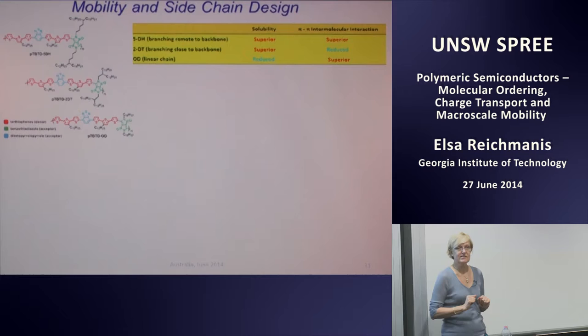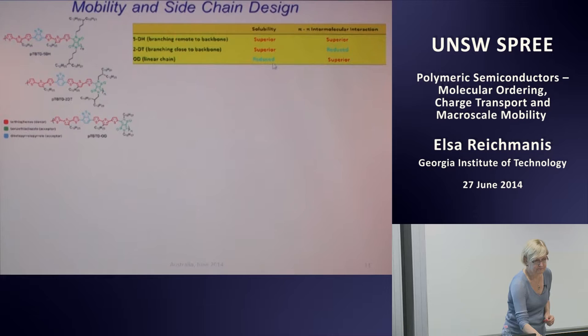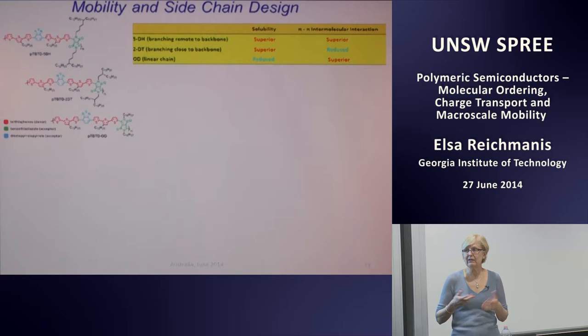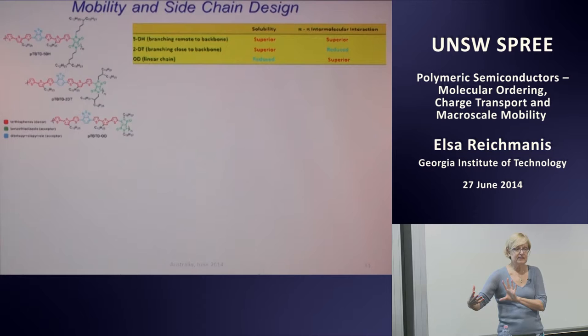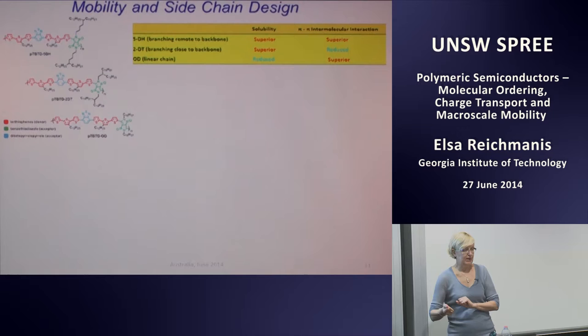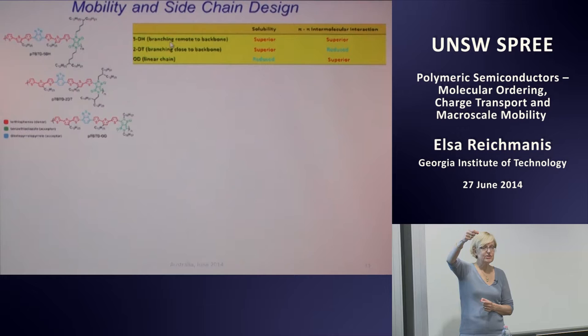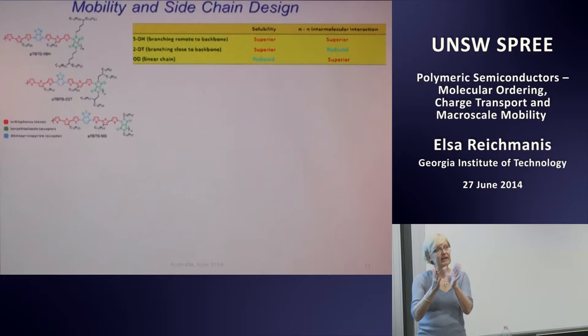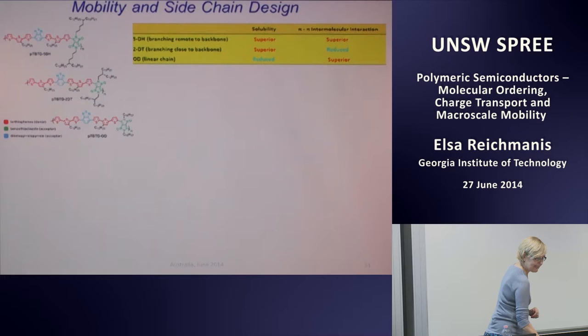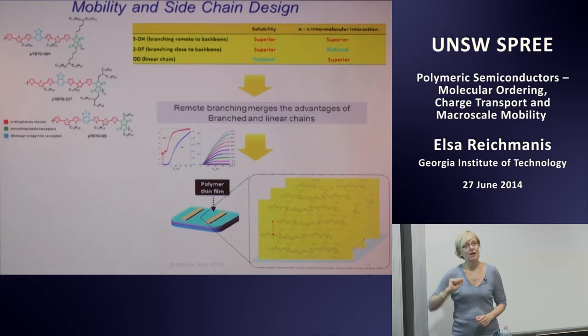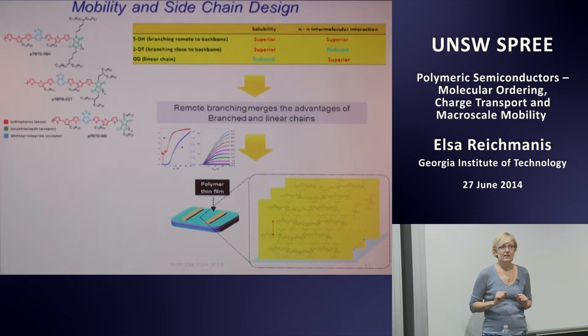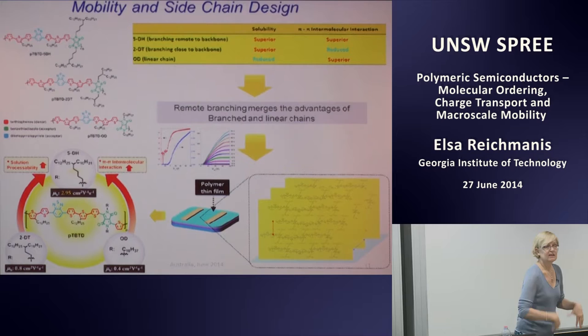From the perspective of the linear chain, it's not as soluble. It doesn't have that additional floppy, organic, greasy stuff. But it does have very good pi-pi stacking where the interactions are superior. All right, so it appears that with that remote branching position, both the solubility and the pi-pi intermolecular distance can be optimized. All right, so does that actually translate into an optimized material from the perspective of at least semiconductor devices? All right, so when we make those devices in thin film form, we actually find that those characteristics do translate.